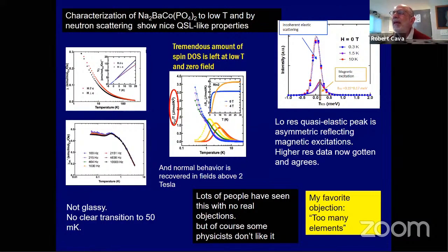Next. So then they did some neutron scattering and some elementary property characterization. And it turns out that down to 50 millikelvin, there's no glassy transition and there's no magnetic ordering. So this sodium 2 barium cobalt phosphate looks to me like it's doing exactly what everybody wants cobalt to do, except it's a triangular lattice. It's not a honeycomb, but triangular lattices are not so bad anyway.